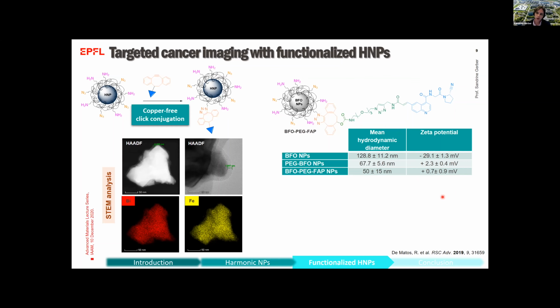By functionalization, we also improved the dispersity of these nanoparticles, which had the tendency to aggregate when they were not coated and functionalized. Here we have the STEM analysis of those nanoparticles, and we see that the coating and functionalization layer is around 8 nanometers.